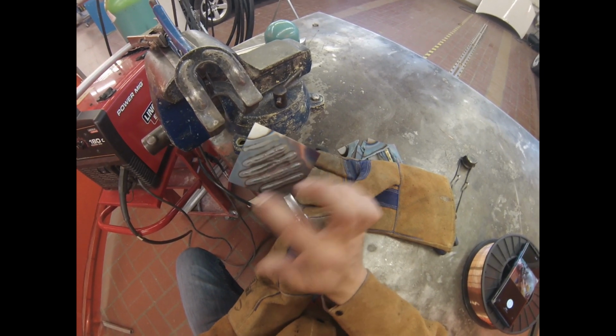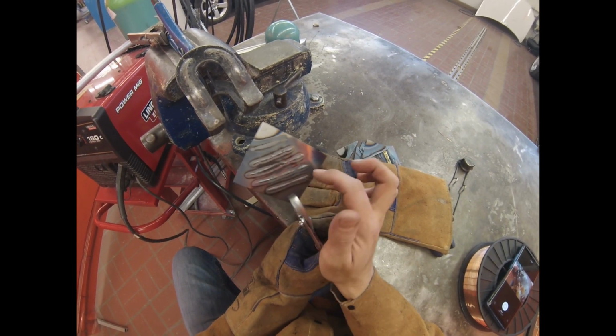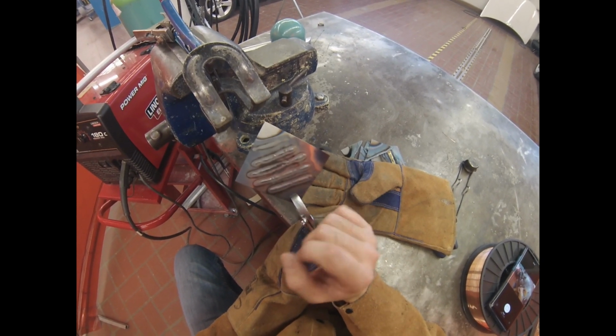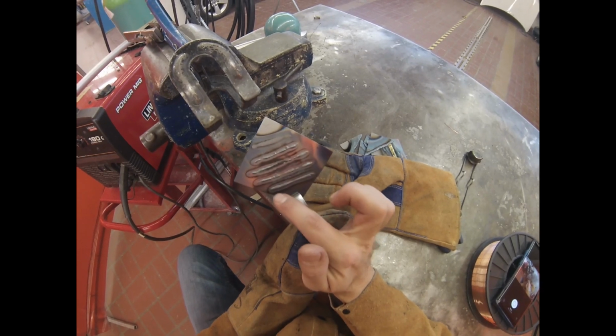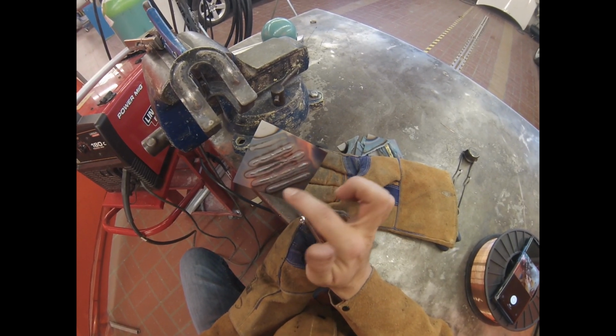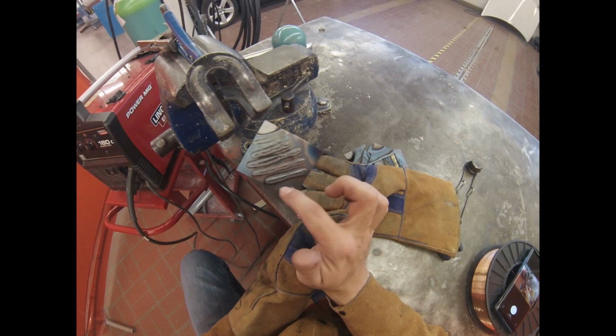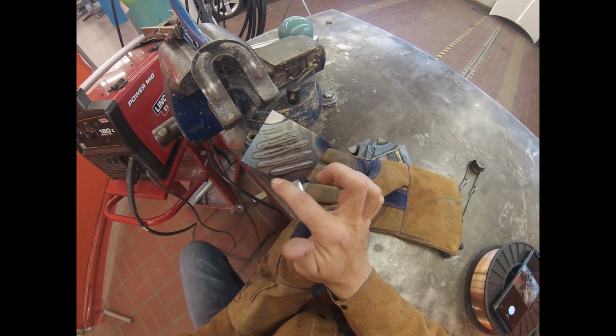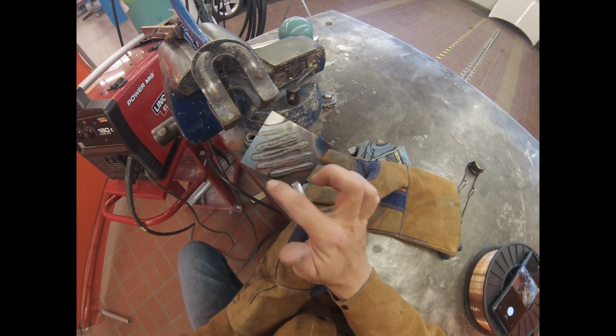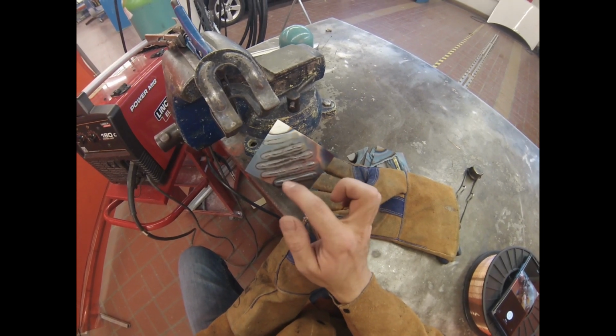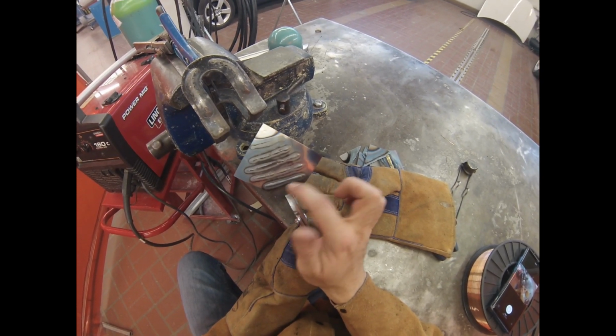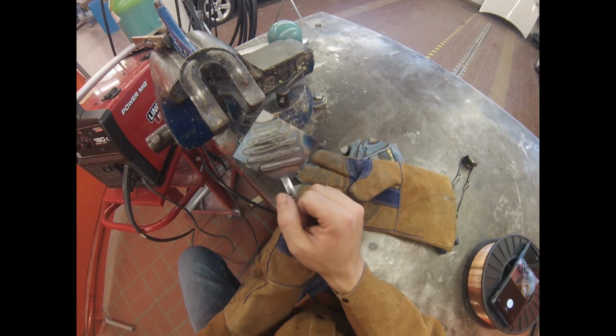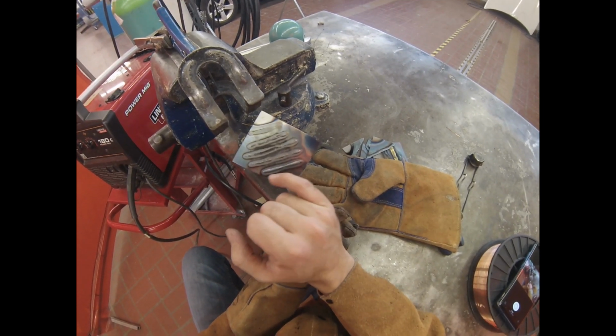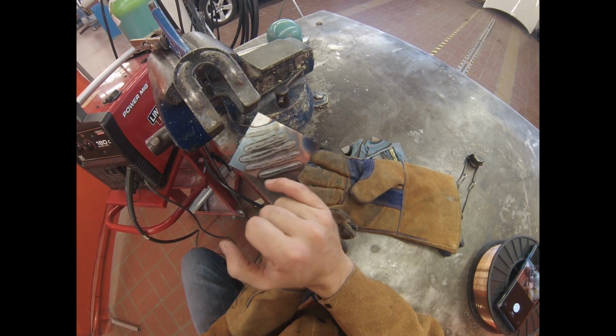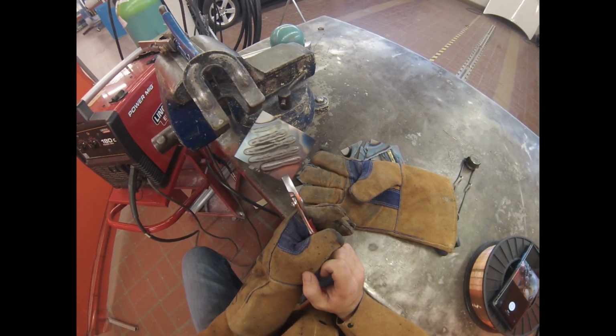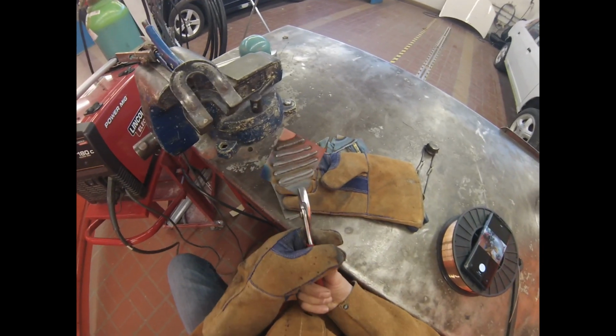It'll crack right beside the weld where the metal has been superheated, but it doesn't have the strength of that high strength welding wire in it, right? If you add more wire, more heat, more weld, and more penetration, you're just adding more heat to the edge, so the edge just cracks sooner, right? So it seems weird, but this is not a strong weld, even though it looks amazing. Too much penetration is not a good thing, because the weld sure is very strong, but right beside the weld in that heat effect zone is where it's going to fail, it's where it's going to break, right?